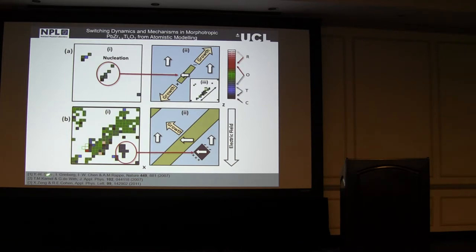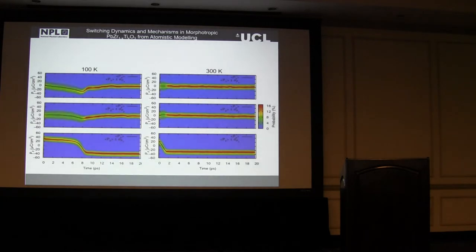What I say about these is, they typically form statistically, but typically we find the ones that stabilize have kind of an octahedral type shape. This is like a three-dimensional equivalent of what was found in this paper here, where you get these beveled domain walls, beveled nucleation sites on 2D domain walls. What we find is that on this kind of nucleus, you get some domain walls which are less energetically favorable than others. If you take these two here, you see the charge, so you've got this particular tail-to-tail domain, and here you've got a head-to-head. They're only just being favorable, so that stimulates growth in these directions, which is exactly what we find. Eventually we can start seeing these 90-degree-ish flavored domains. These are locally orthorhombic, and this is locally tetragonal. Eventually you start having this which then grows in a conventional manner, and as these domain walls start to merge, it then flips around to being fully polarized.